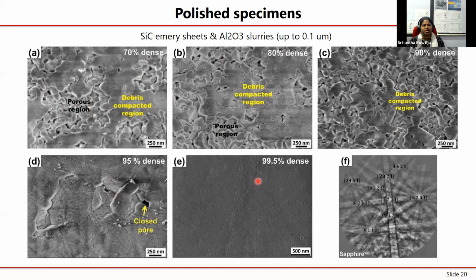However, for 95%, 99% and 99.5% samples, predominantly the samples have quite smooth surfaces. This is not very representative. I am just trying to show that for the 95% dense sample, there are a few places with a small amount of porosity, and this could be a closed pore, but due to the polishing, that closed pore would have opened up on the surface. And this is the Kikuchi pattern I am showing for the sapphire, which is a single crystal, because that was used as a reference when we did the tribological testing of these five materials.